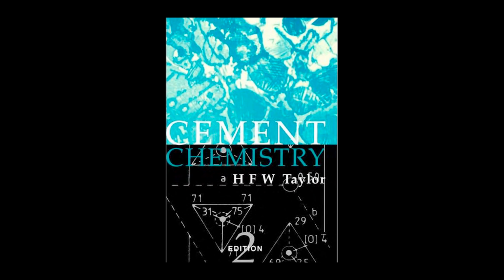The sulfate ions react with the calcium aluminate hydrates and the calcium hydroxide to form two secondary voluminous phases, secondary gypsum and additional ettringite. The crystallization pressure exerted by the growth of these secondary expansive crystals is what causes cracking, scaling, and eventual failure of the cement paste structure.